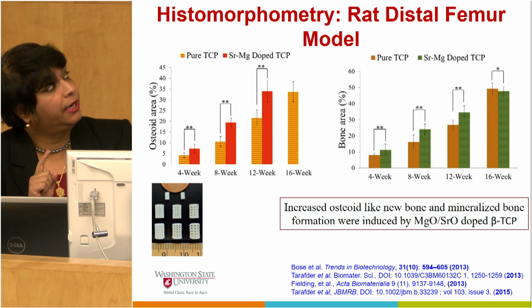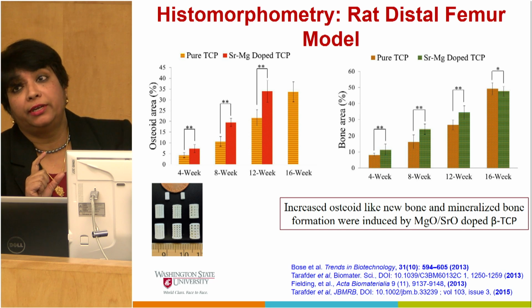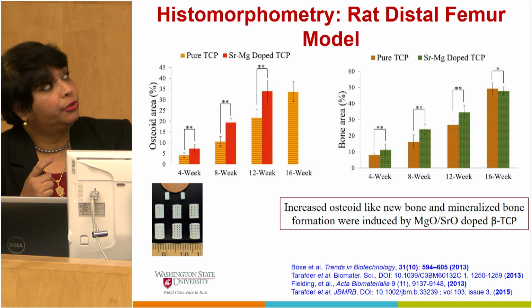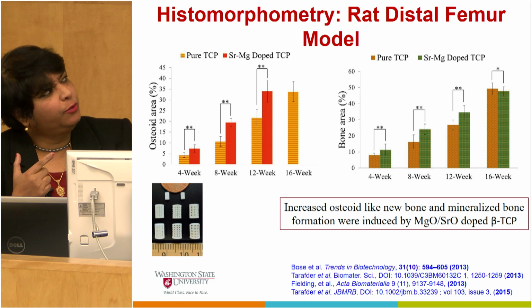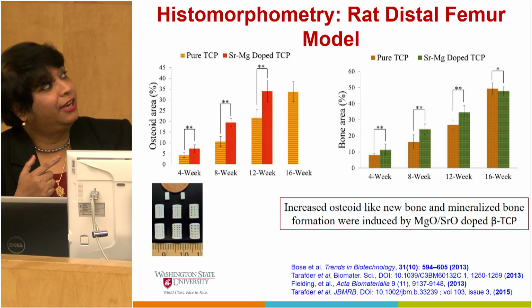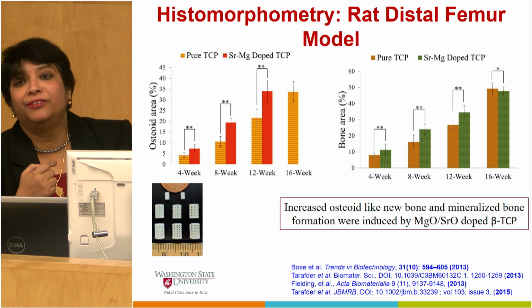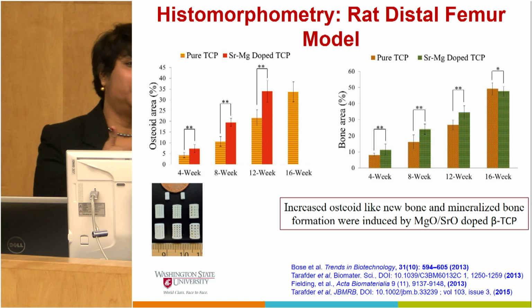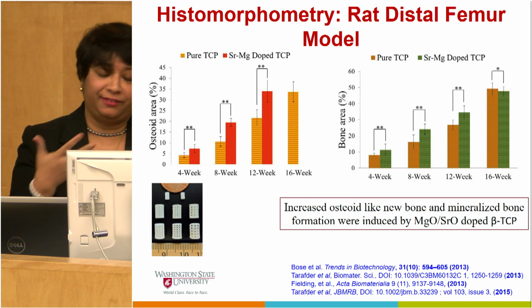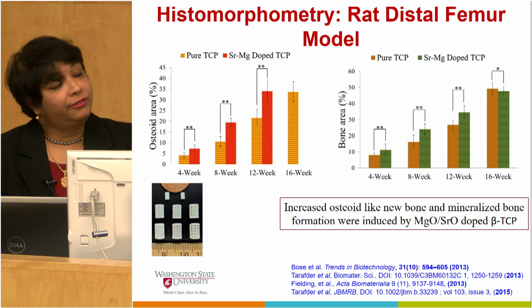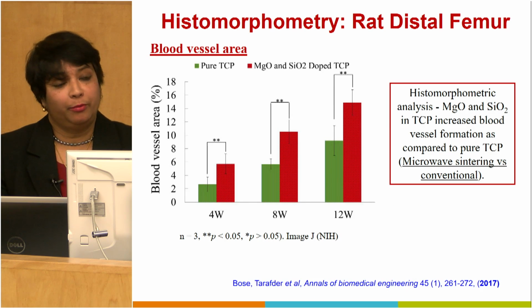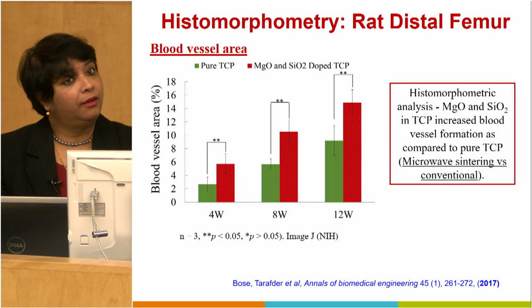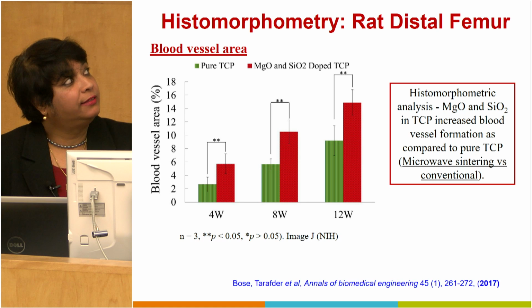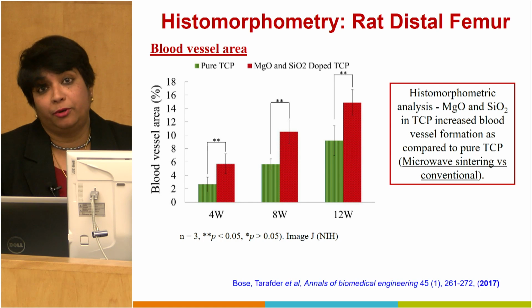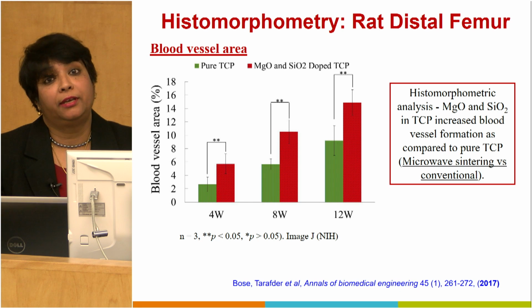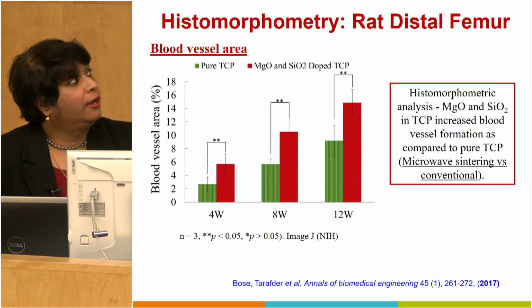In the 4-week to 16-week study, in all cases we saw that the chemistry modified scaffold showed higher bone growth and bone area. At 16 weeks you are seeing only the orange line on the left hand side plot because we could not differentiate the newly grown bone after 16 weeks. It was amazing to see. We also looked at blood vessel formation. Blood vessel formation is needed for any defect to heal in our body, and we saw that chemistry has a tremendous effect on blood vessel formation within these porous 3D printed bone-like scaffolds compared to the control, which is the green bar.